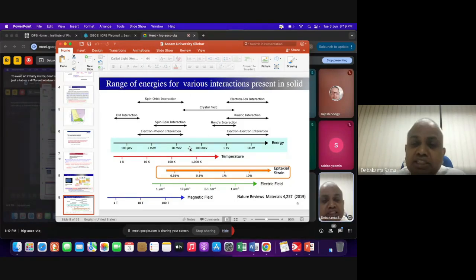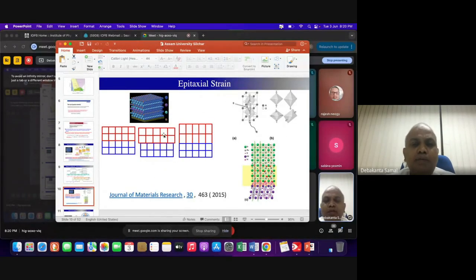So by playing with the strain, by playing Lego with the atomic layers, you can create various new phenomena which nature has not provided. You can actually discover new materials which you cannot find in nature. This is what I was talking about: strain, Lego. Suppose the blue one is one atomic layer and the red one is another atomic layer. If both have the same lattice parameter, then there is no strain, because one is sitting on top of the other, like two cubes. One cube sits on top of another, the lattice parameter is the same, and there is no strain.